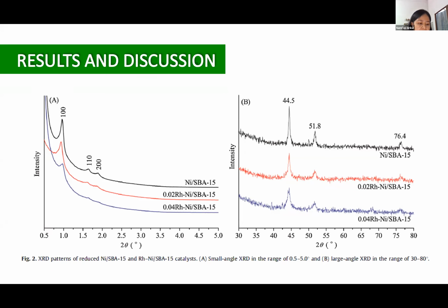Figure 3 shows the TEM image of the reduced nickel on SBA-15 and rhodium nickel on SBA-15 samples. It can be concluded that the presence of rhodium in nickel catalyst leads to a decrease of the nickel particle size. Addition of a small amount of rhodium to the monometallic nickel catalyst leads to an increase of the initial activity. The yield of hydrogen and carbon monoxide as a function of time on stream for the first 30 hours is presented in figure 4.